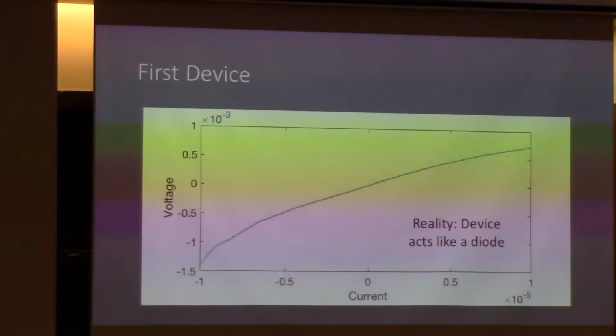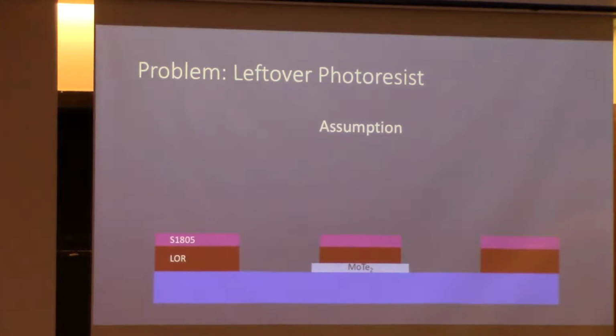The problem is that when we were doing this photolithography step, when we developed away the spots that we had shown UV light on, we assumed that all the photoresist went away, it's perfect, it's all gone, no issues. In reality, what probably happened is that not all the photoresist dissolves, and there's some left between the contacts in my sample. So I need another way to ensure that all this leftover photoresist has been taken off.